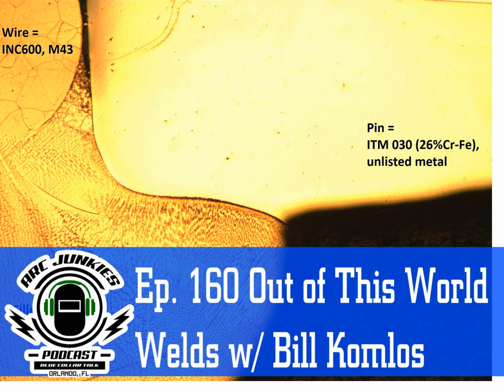These aren't full pen tests, right? You're like a fillet weld. The fillet weld is a shear. And we don't test fillet welds to test the strength. We just beat them over to see if there are discontinuities in there, right? Sheet metal, same thing. None of our sheet metal tests are tested for strength because they're so ductile. You're not going to get a valid strength test out of it anyway. We just beat it apart to see if we got discontinuities and if our arc spot weld diameter is as big as it's supposed to be.